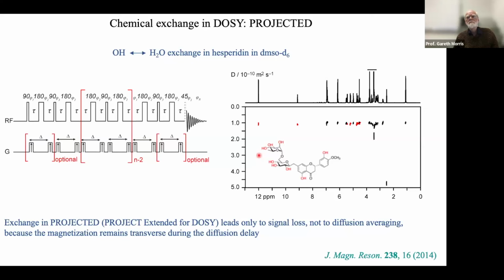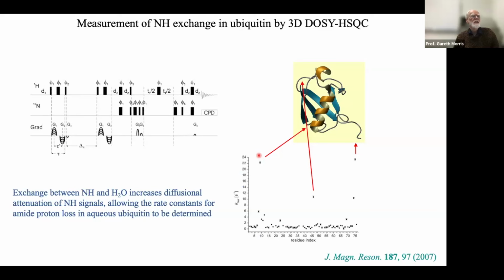Of course, having exchange can be useful to us. We can actually use diffusion measurements as a way of measuring exchange rates. Here's an old example from a collaboration with Stefan Berger, in which we measured the rates of NH proton exchange in different parts of the ubiquitin molecule. Unsurprisingly, the terminus has rapid exchange, but we also have rapid exchange where we have turns which are solvent exposed.